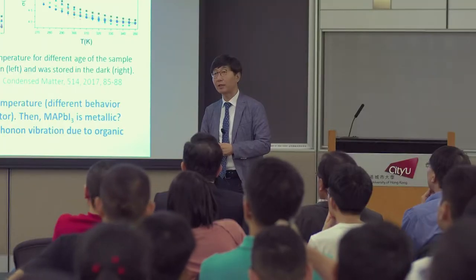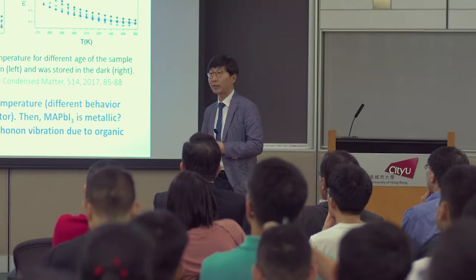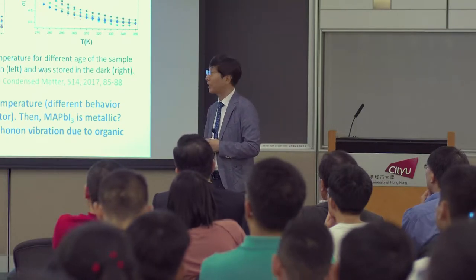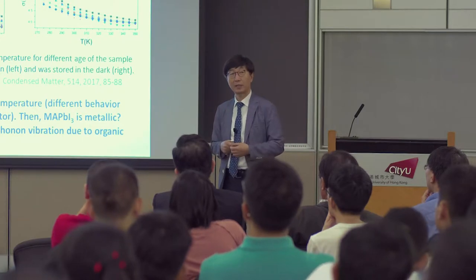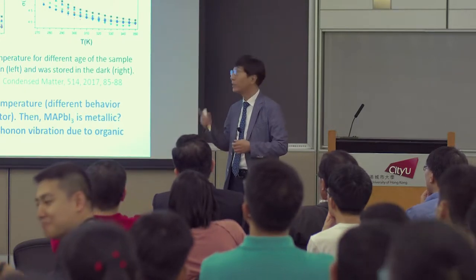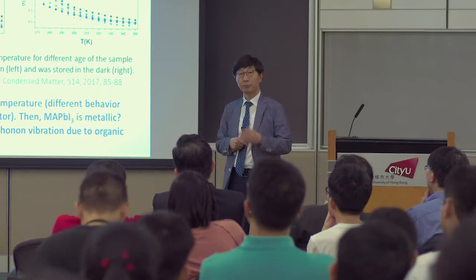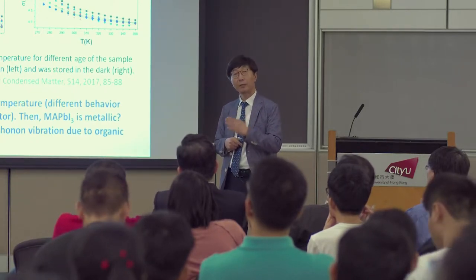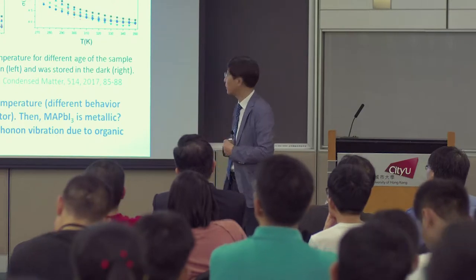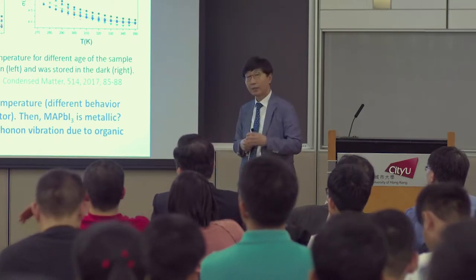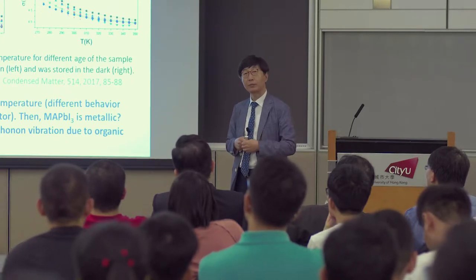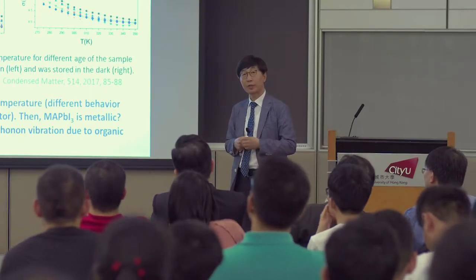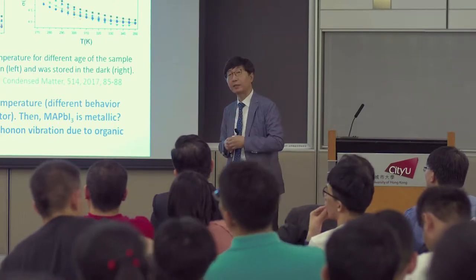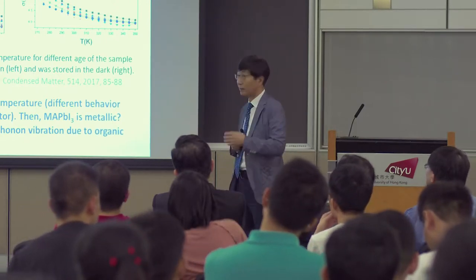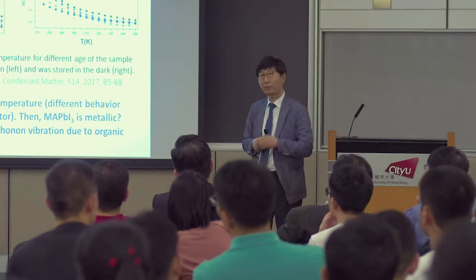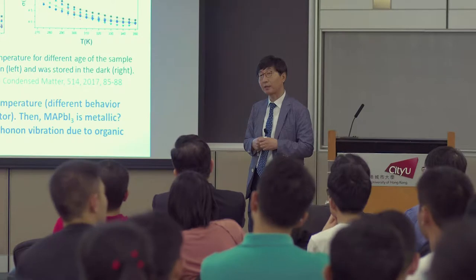So the question is, is MAPbI3, methyl ammonium lead iodide, metallic? It is not metallic; it's an insulator to a semiconductor. So why? The behavior of the electrical conductivity with temperature looks like metallic behavior, which is probably because the molecular vibration of the A-site cation, even at room temperature, can initiate or accelerate the phonon vibration. So probably the electron will be scattered by this phonon vibration.